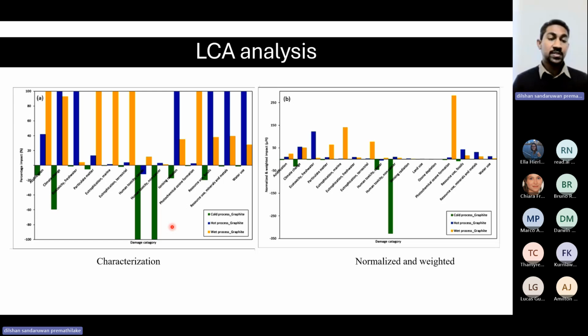However, the hot process and the wet process derived graphite show really high environmental impact. You can see that under different impact categories, I can see higher impact is given off through these two materials. Basically, for the hot process, this is because of the large amount of heat I used and also the electricity that I use. For the wet process, this is mainly due to the acid reagents that I have used for the treatment. And the normalization and weighted impact categories showed me that largely it's going to be the wet process that's going to give us the highest impact, rather than the hot process derived graphite and the cold process derived graphite.